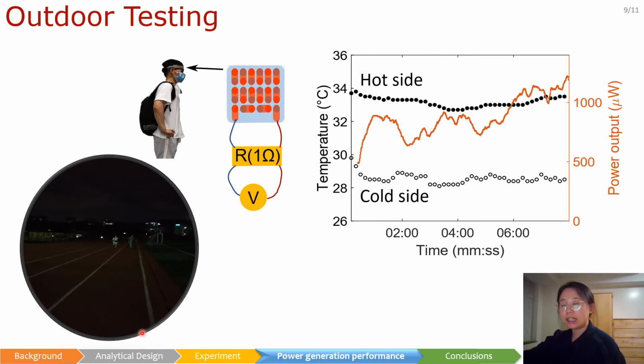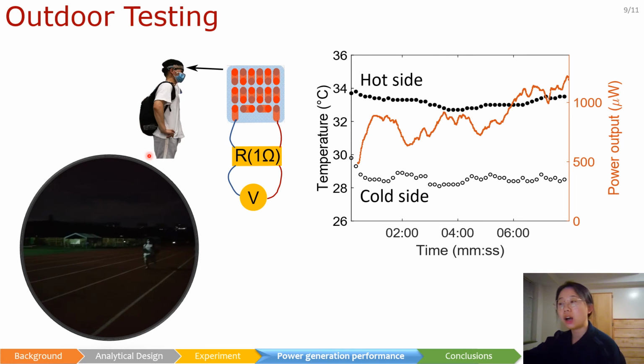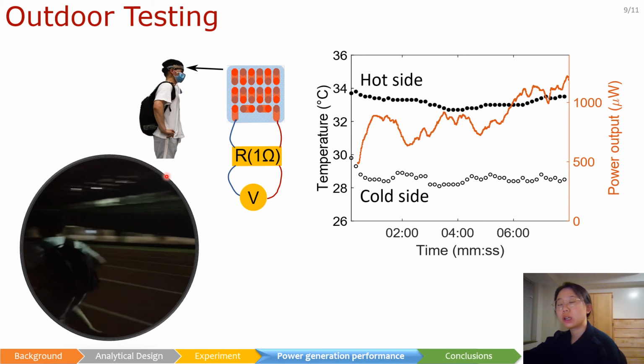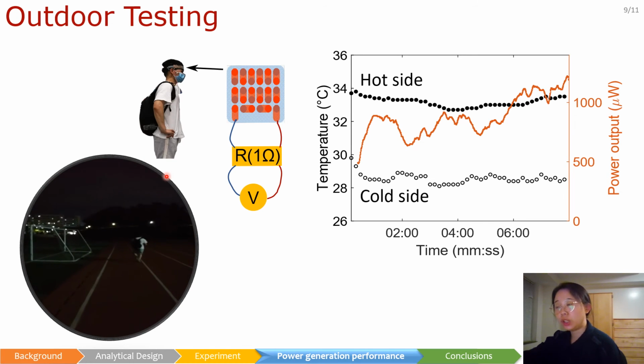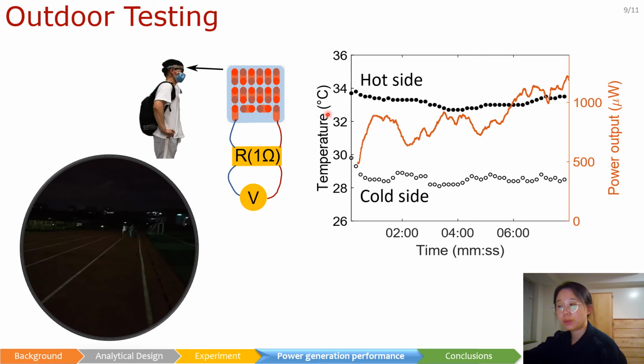In outdoor testing, the headband wearer carries a portable data logger in a backpack and runs outdoors. Like in indoor testing, two thermocouples are attached to a top electrode and a bottom electrode, recording temperatures. The headband is connected to an external resistance of 1 ohm for impedance matching, and the output voltage is being monitored by the data logger. Figures on the right show our headband with 50 pairs of thermoelectric units can generate a power up to 1.2 milliwatts during an outdoor jog at night at a temperature of 25 degrees C.